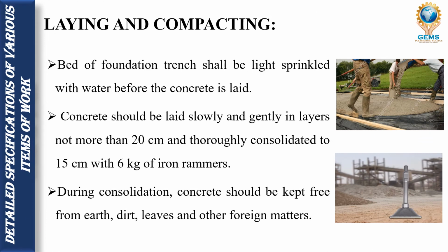Then next one is what? Laying and compacting. The bed of foundation trench shall be lightly sprinkled with water before the concrete is laid. Okay, before laying a concrete, water should be sprinkled in the bed of the foundation trench. Then the second point is what? The concrete should be laid slowly and gently in layers, not more than 20 centimeters. We need to gently lay the concrete.